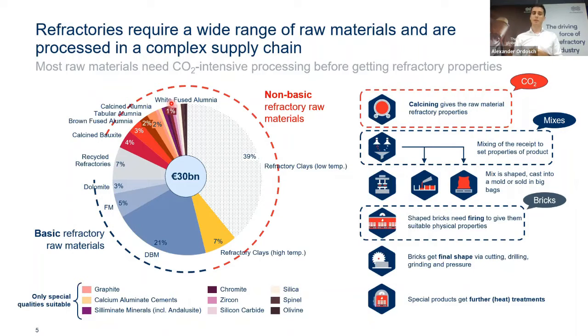And a similar approach also applies to a lot of non-basic refractory raw materials. You have to burn, for example, fire clay to chamotte. You have to calcine bauxite. You have to increase the grain size and all of that. Once you process your raw material, you can crush it, you can grind it and so on, and you can mix it with a certain recipe. And with this recipe, you basically adjust the physical characteristics of your product.